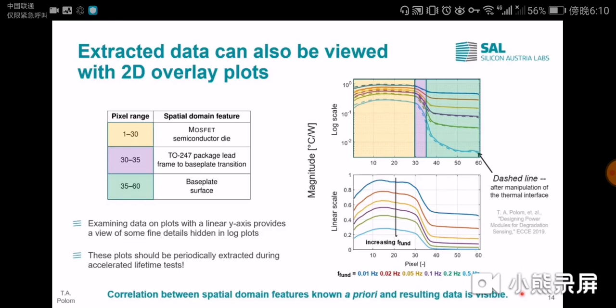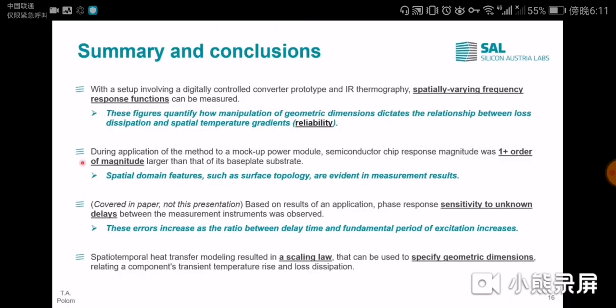A final thing that I want to mention is the dashed line in this top plot. This was after manipulation of the thermal interface between the MOSFET and the base plate. This was covered in another paper, but what I want to highlight and emphasize is that these plots, really we should be periodically extracting them during accelerated lifetime tests for comprehensive characterization of what thermal mechanical stress is doing to our assemblies. To conclude, with a setup involving a digitally controlled converter and infrared thermography, we were able to make measurements of spatially varying frequency response functions.